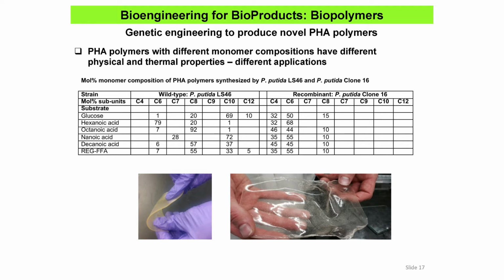And the interesting thing is that now this is a mixture of short chain and medium chain PHAs, with a large portion of C4 and C6 and a little bit of C10 in these ones, but not here. So these might have physical and thermal properties that are more interesting in terms of competing with petroplastics, with polyethylene or polypropylene. Well, we're still working on these. We still have to determine their physical and thermal properties to see how they behave.